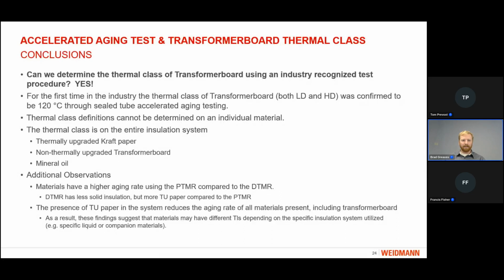With a thermal index of 110, as Tom described, adding 10 degrees to that establishes the thermal class of 120. However, in defining the thermal class of the transformer board specifically, we actually learned that thermal class definitions cannot be determined on an individual material. The thermal class is really on the entire insulation system. In the instance of the industry proven system, that is thermally upgraded kraft paper, the non-thermally upgraded transformer board, and mineral oil. Based on what we learned about the presence of the thermally upgraded kraft paper and its impact on the aging characteristics of the non-thermally upgraded board, these systems must be tested and defined as the entire system and not the individual components.